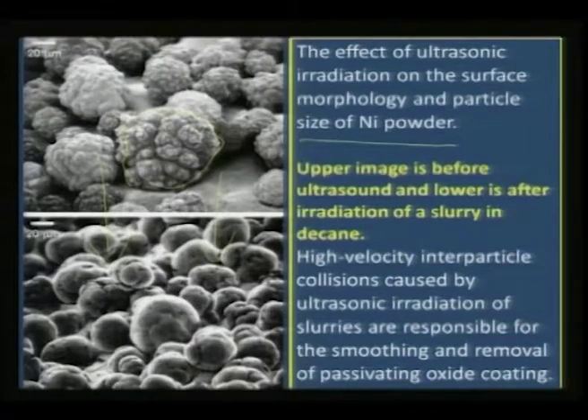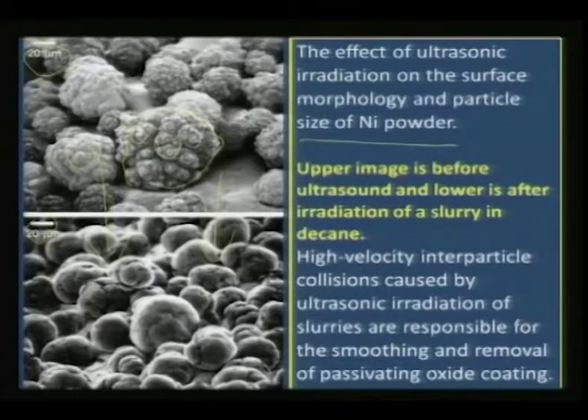Now you take the same powder and try to sonicate it. You can see after sonication, or exposing it to a slurry of nickel particles, they all look modified in surface, and they seem to have been also broken, because both are on the same scale bar. So you see that these clusters seemingly are broken and they are polished. Now what is the influence? You see that once you sonicate this ordinary nickel powder and use it for your reactions, the reactions are much more effective and they are nearly comparable to the Raney nickel.